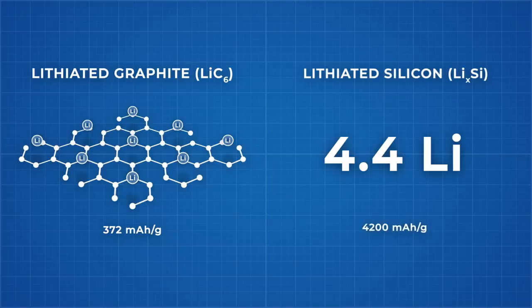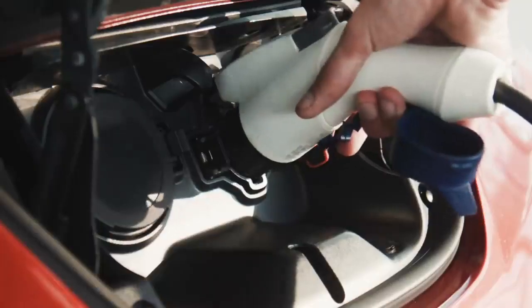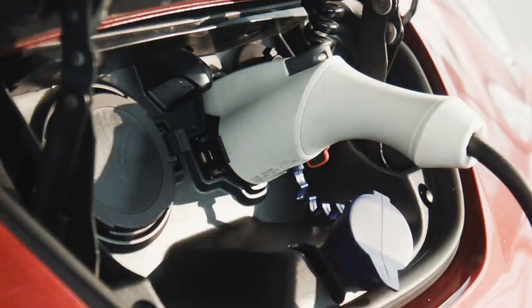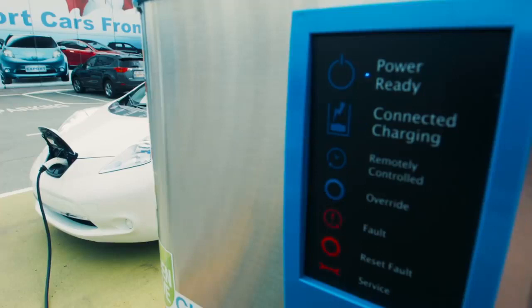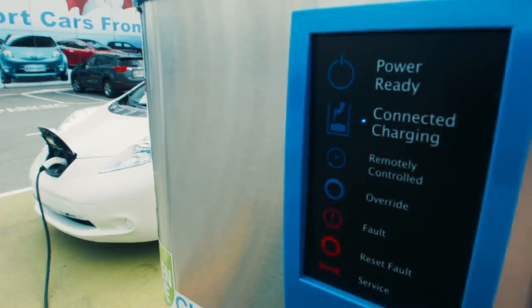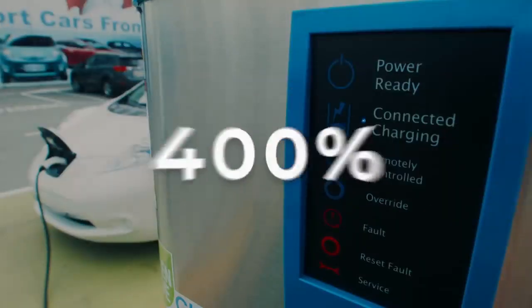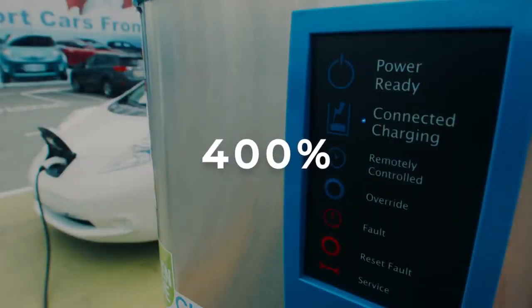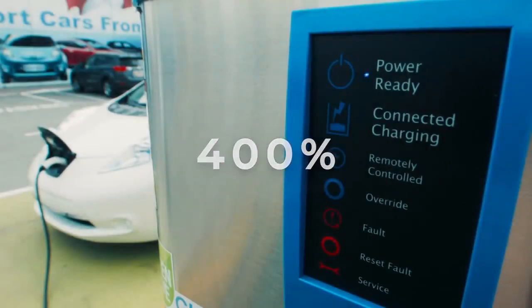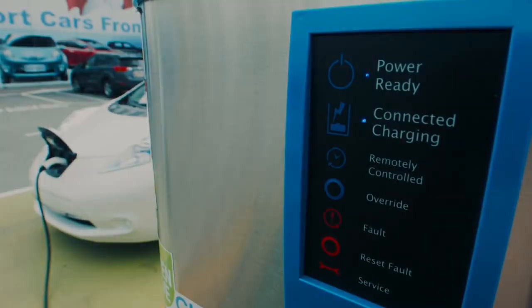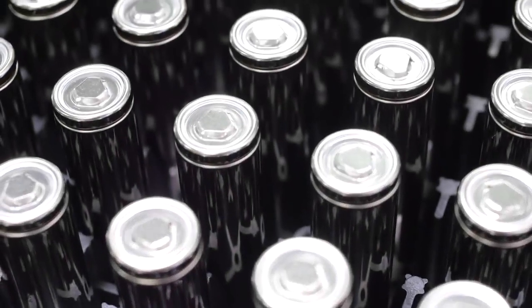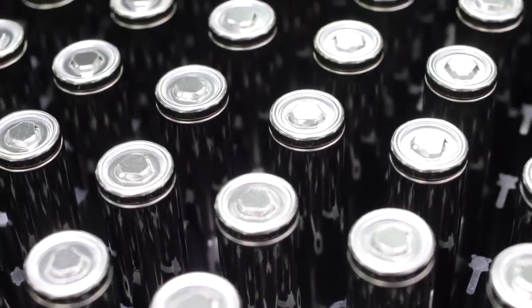This seems great and can provide increases in battery capacity, but it also comes with drawbacks, as those 4.4 lithium ions lodging themselves into the silicon crystal lattice causes a volume expansion of 400% when charging from empty to full. This expansion creates stress within the battery that damages the anode material that will eventually destroy the battery's capacity over repeated cycles.